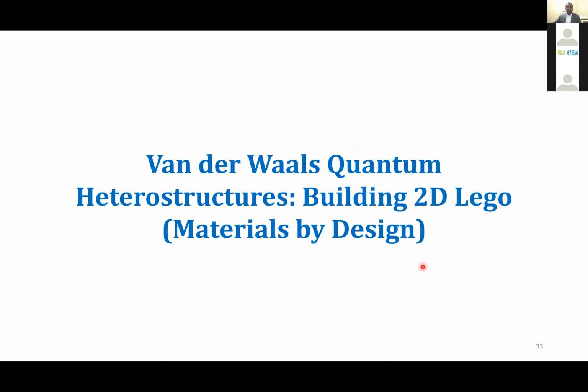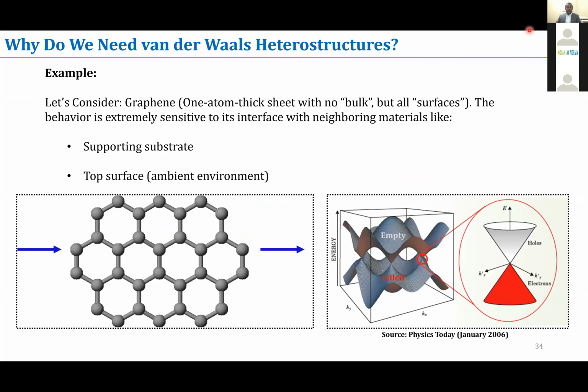So with the formation of these two-dimensional materials like graphene and boron nitride, now let's look at how we can build heterostructures out of these 2D materials. That is because graphene is chemically inert, however it's very sensitive. You can think of it like a paper, or a very thin layer: if you put it on any substrate, it will try to conform to that substrate. Anything on top of graphene or at the bottom can influence its energy band gap, its electronic conductivity, or also its mechanical properties.